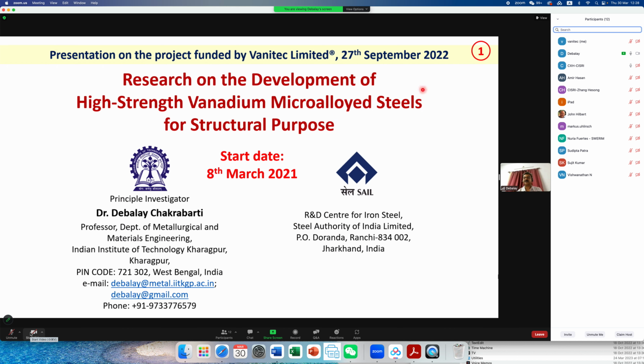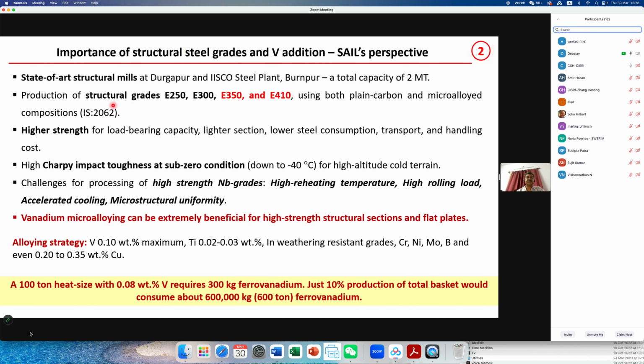This is the project: Development of high strength vanadium microalloyed steel for structural application. The objective is to develop high strength structural steels, 350 onward, 350, 410, 450 like that. Niobium has certain disadvantages that we know: high reheating temperature, high rolling load, accelerated cooling, and microstructural uniformity. Grain size uniformity is a problem. These kind of steels require high strength and high impact toughness down to quite a low temperature for use in